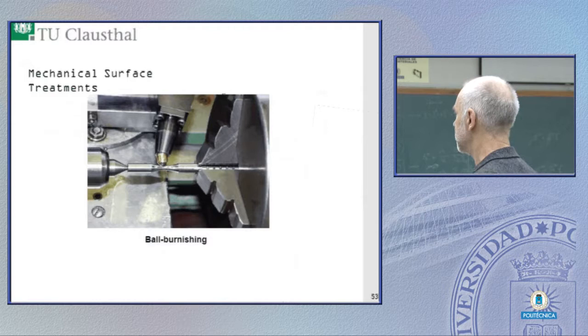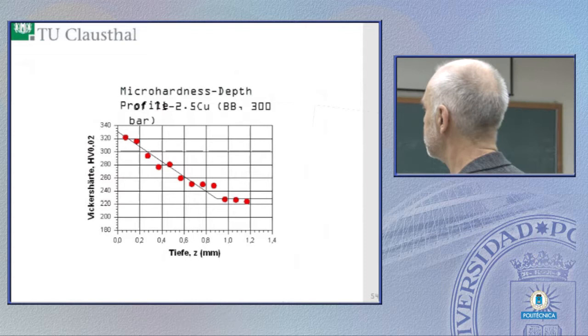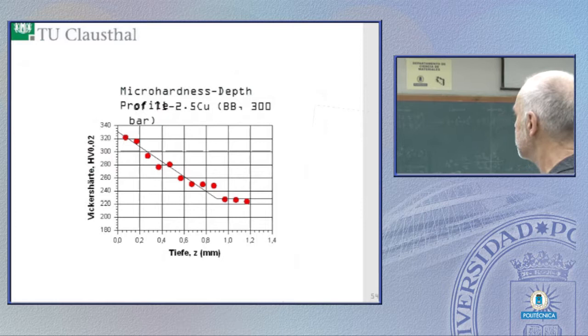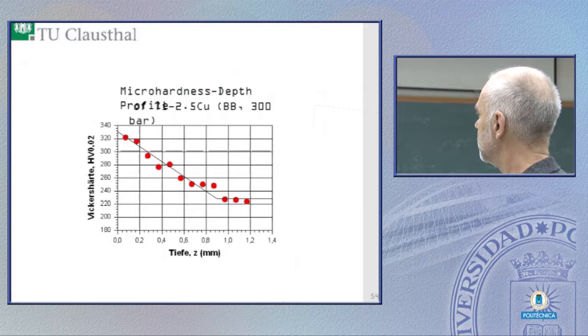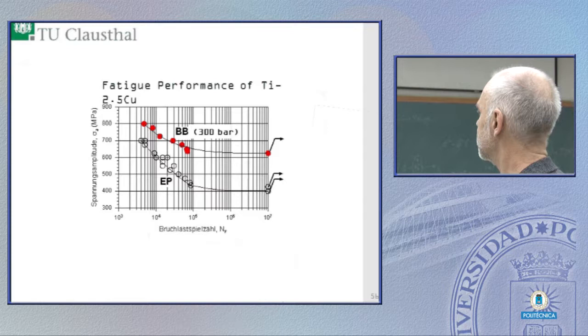You can do it 4 times, you can do it 8 times, and this gives rise to special deformation degrees, dislocation densities, and so on in the microstructure. Some properties are better compared to the properties produced by other deformation processes. But, for example, the introduced residual stresses are not very stable. We could prove it by means of thermal processes, heat treatment. It's not always the best structure, it depends, and this method is not very useful for the industry.